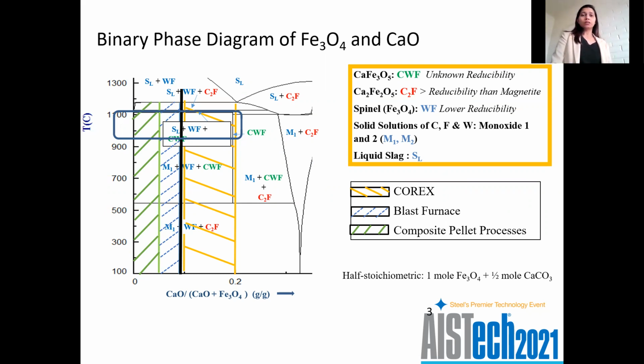So this is a simple binary phase diagram of magnetite and lime. What it shows here is that this CWF phase is a stoichiometric compound of 1 mole of magnetite, 1 mole of lime. It forms at about 28% of lime. The diagram is also superimposed with the lime requirement of different iron making processes. So for the blast furnace, we have the lime in the range of about half stoichiometry LMP, which is 1 mole magnetite, half mole lime or limestone. And that's why we have selected this half stoichiometry composition for our pilot testing experiments.